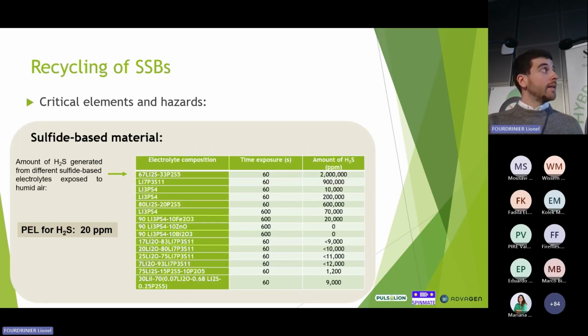We can see in the next slide. In this table, you can see the amount of hydrogen sulfide that is generated by exposing different kinds of sulfide-based electrolyte to moisture just for a few seconds or a few minutes. You can see you can have up to 2 million ppm of hydrogen sulfide, and the permissible exposure limit for the hydrogen sulfide is just 20 ppm. So this is also something that we need to take into account.